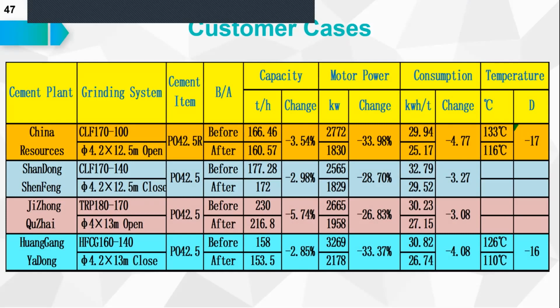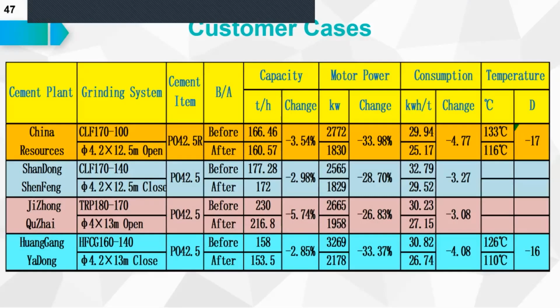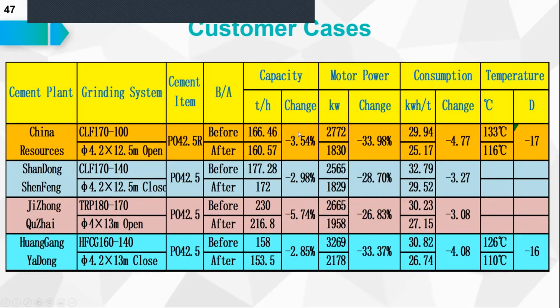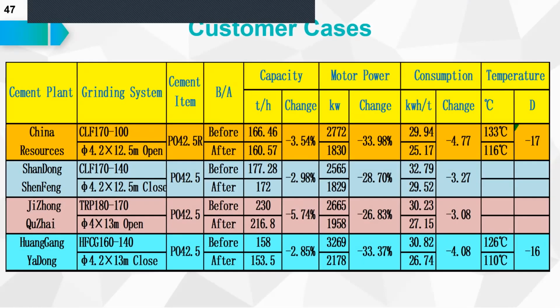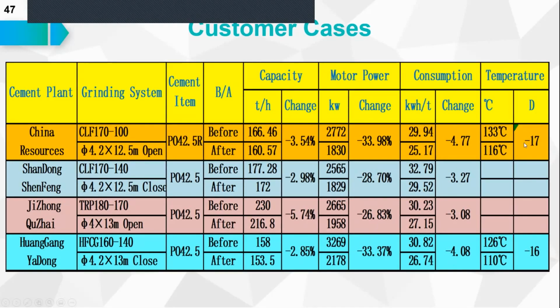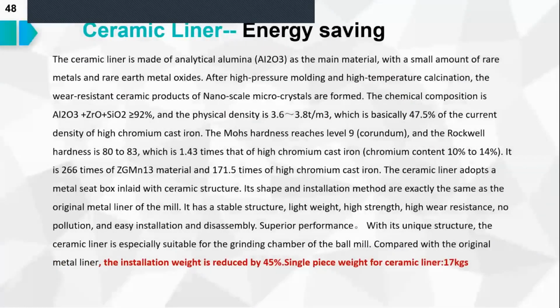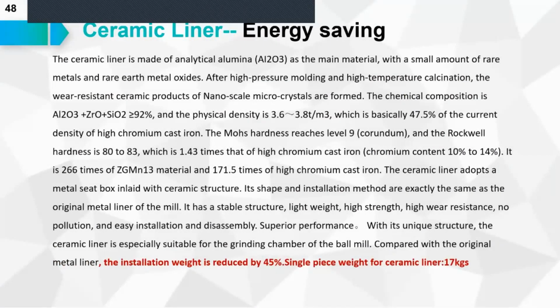Here are some customer cases. We can easily see the equipment and cement type, and the capacity usually will be controlled within 5%, decreased about 5% normally, some without change. It depends on the grinding ability, which sometimes has a big influence, even without changing any grinding media. So we will control about 5%, and the power usually will be decreased about 25 to 35%. The consumption per ton of cement is going to be decreased by 3 to 5 kilowatt, and the temperature will be decreased also. Here is the ceramic ball replacing the steel ball. We can see.